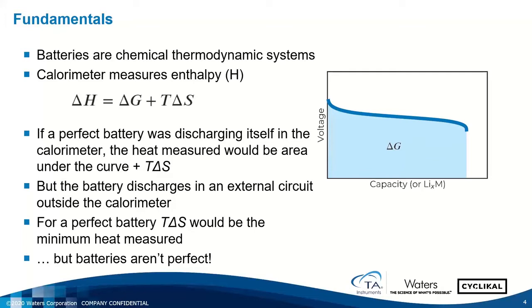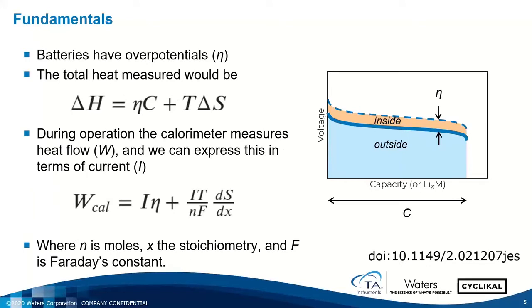And so the heat from the work, the free energy, is not measured by the calorimeter. And so for a perfect battery, the change in entropy would be the minimal heat measured. But batteries aren't perfect. And so in reality, what we end up having is there's overpotentials in cells. So the reason for an overpotential is typically internal resistance. So you can sort of think of it as friction to operating the battery.